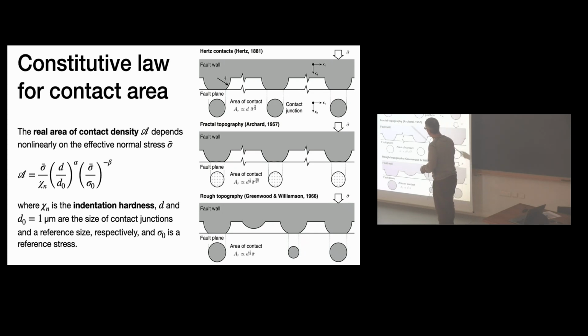And so there is a lot of theoretical work that describe the nature of this contact and how much area of contact we should expect from the topology of these surfaces. The simplest one is a collection of what we call Hertz contact, after the name of the physicist who described these. These are simple elastic spheres under pressure that are pressed into each other or against a rigid wall. And when you do that, it creates an area of contact that can be resolved analytically. And when that's the case, it's proportional to the normal stress that is applied normal to the interface to the power of 2/3.